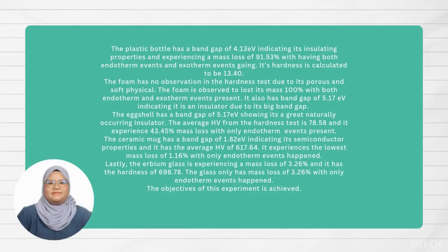The ceramic mug has a band gap of 1.82 eV, indicating its semiconductor properties, and it has the average HV of 617.64. It experiences the lowest mass loss of 1.16% with only endotherm events happening. And lastly, the erbium glass is experiencing a mass loss of 3.26% and it has a hardness of 698.78. The glass only has mass loss of 3.26% with only endotherm events happening. The objective of this experiment is achieved.